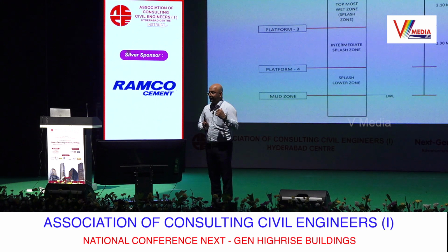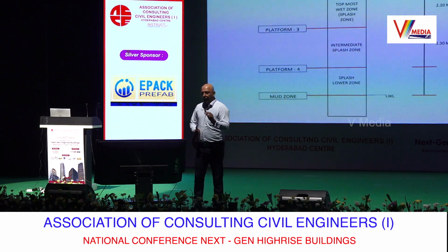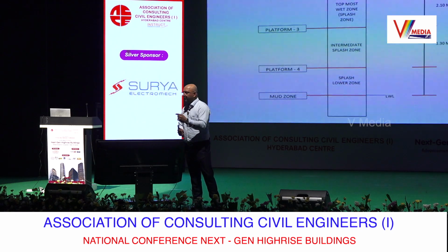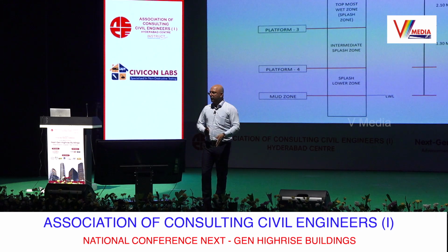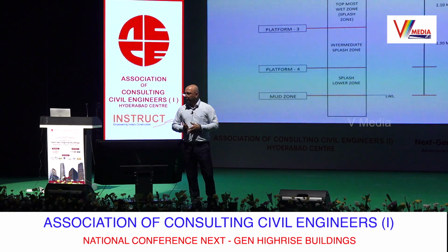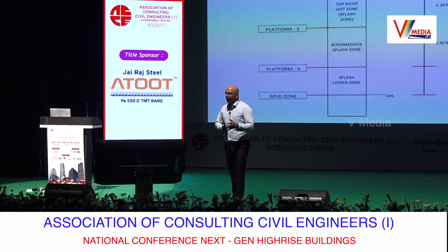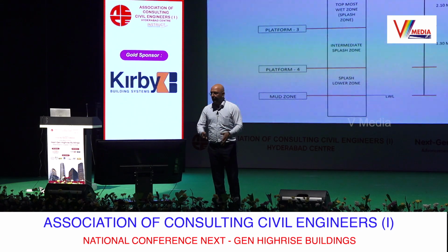And when we did some underwater testing, we physically checked by tapping. In some places we could hear a hollow sound, and in some places we could see holes. So that is where we initially did some endoscopy through those holes. And when we found there were large gaps in that concrete, we removed the steel by underwater cutting, and we found these damages. Now how do you repair those? For that, we have evolved a technique of pile encapsulation, which can be done underwater with divers.